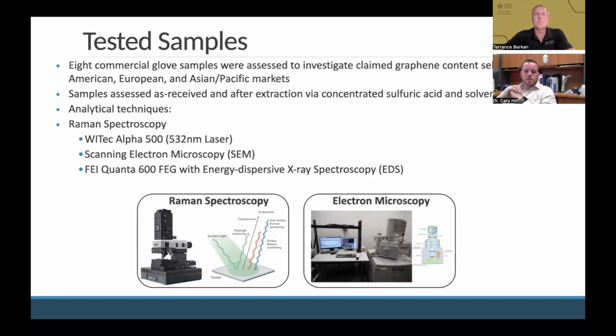And so the purpose there being that we're seeing the fibers as they're received. So if anything's on the surface, we should be able to see it and characterize it. If it's within the fiber, it's released and we're able to analyze it there. Our concentration was on the fibers themselves because that's where the advertised graphene content was located. We did not concentrate specifically on the rubberized material, though we did still analyze it. So just to be clear there, this is based on a fiber application because that's where the advertised material is presented.